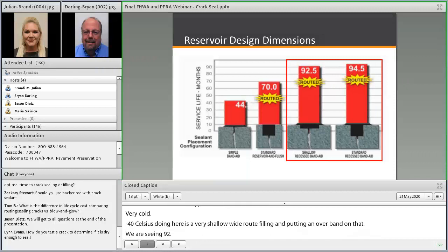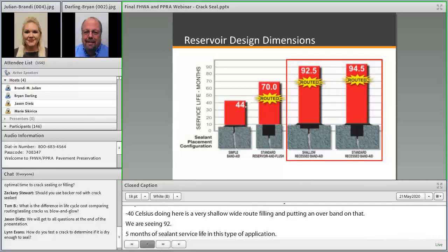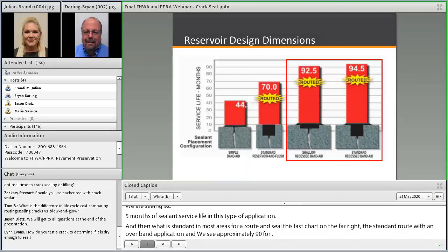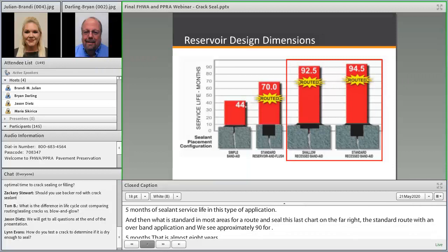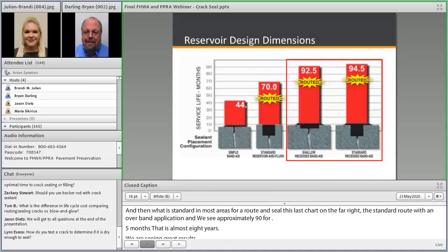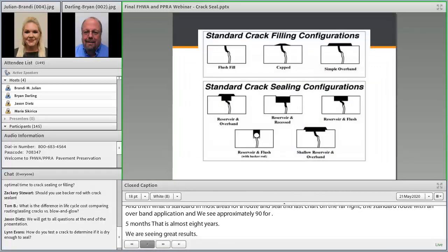And then what is standard in most areas for a route and seal is this last chart here on the far right. Standard route with an overband application, and we see approximately 94.5 months. So that's almost 8 years. So we're seeing great results. So there is definitely a correlation between the type of installation and the performance you're going to get out of it. And this is the next look at some of the other types of crack sealing configurations.